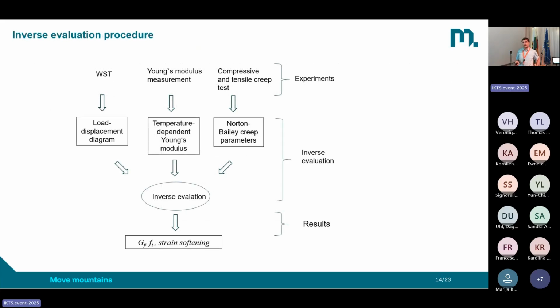One possibility is to again use a simulation to determine accurate values. How is it done? We take the result from the wedge splitting test, the load displacement diagram. You already saw that. But then we additionally do a Young's modulus measurement to have the input Young's modulus of the material. And at high temperatures, there is also this deformation under constant load, which is called creep. This may also play a role. So we do these measurements beforehand so that we have this data. And then we start an inverse evaluation to determine the specific fracture energy, tensile strength, and the strain softening behavior. How does it work?